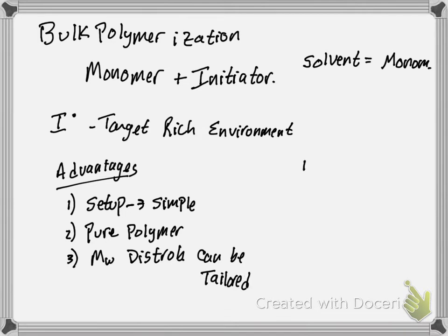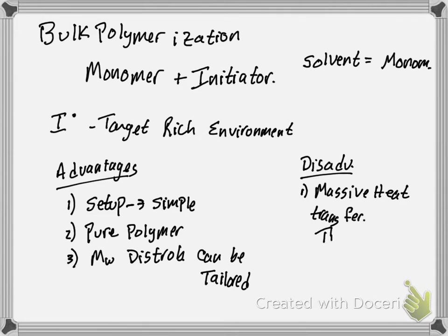All right, disadvantages. And this is considerable. Bulk polymerization is not the best for doing a lot of polymerizations. You have massive heat transfer issues. Remember the Tromsdorf effect? Or thermal runaway? Very commonly seen in bulk polymerizations.